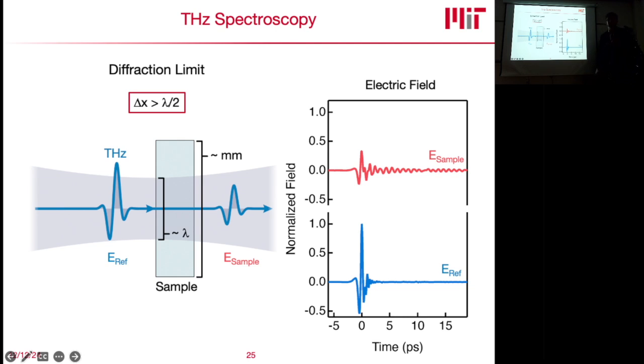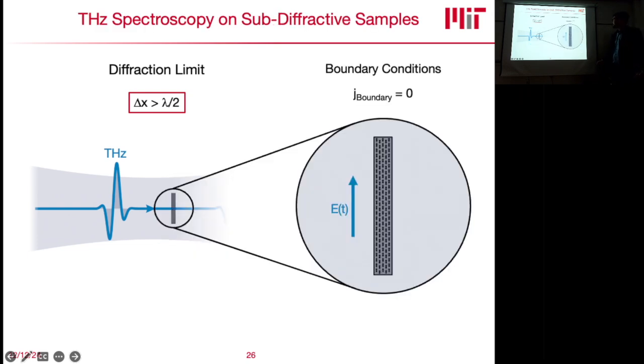So the main difference is that now the edges of your sample are basically encompassed fully into your beam. Because here your edges are so far away from whatever's happening here, your responses in the material don't care about the geometry of the sample at all. And since it is a Gaussian beam profile, it's very smoothly defined in this case. But yeah, that is indeed the case. So the homogeneity of the field doesn't really matter that much. And so this is a situation that could arise now.